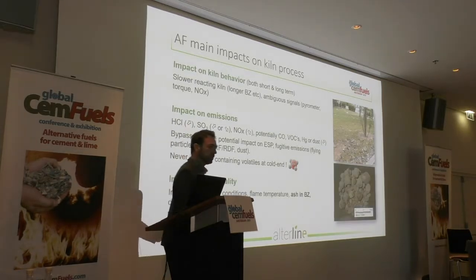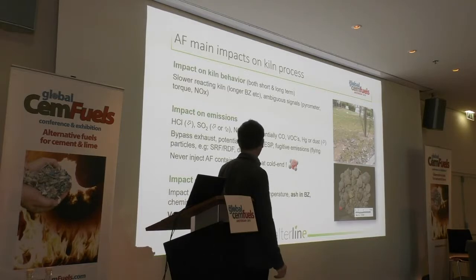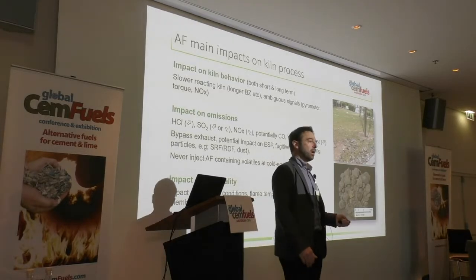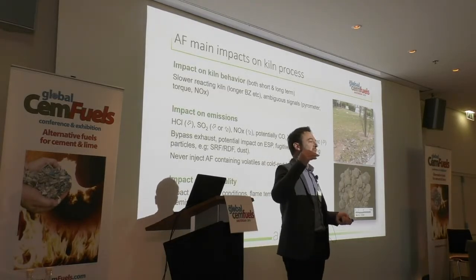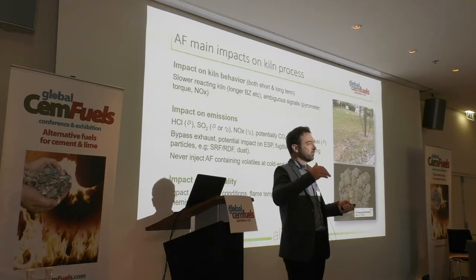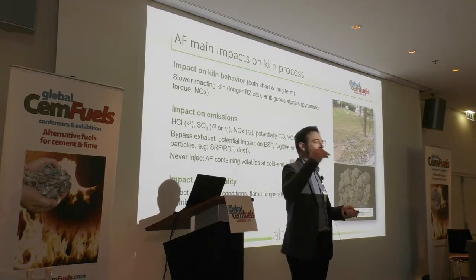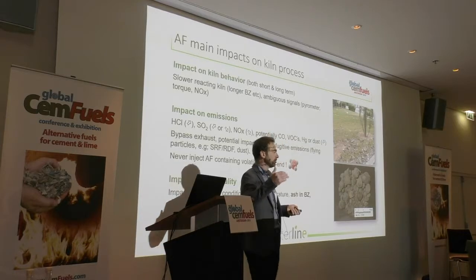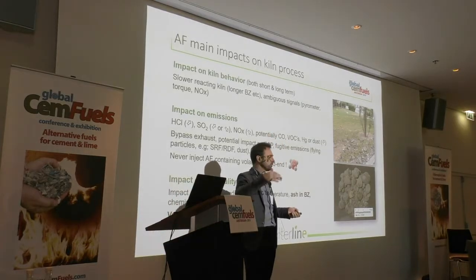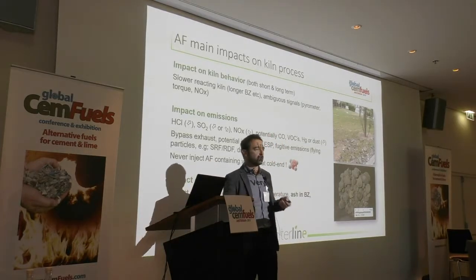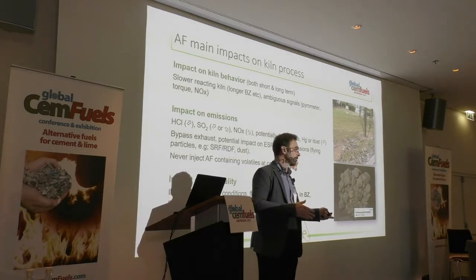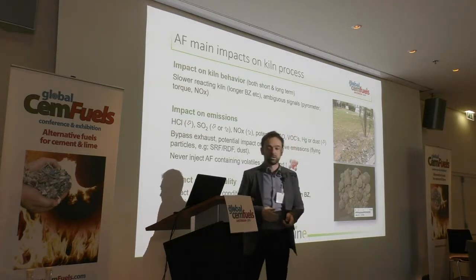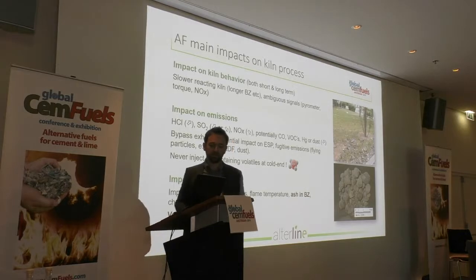Okay, impact on quality can be reduced clinker. At a certain level of alternative fuel, the ash volume and the ash composition start to be very important, especially with dried sludge, for instance, ashy fuels. And you need to compensate it by preparing the raw meal correctly. So it's important to keep in mind.